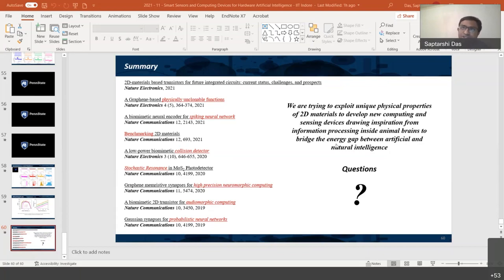But as you know, trapping and detrapping also has some other issues, which is the endurance, how many times you can cycle. That's a problem with NAND flash memories. You can hardly do 10^6. In our lab, we have been able to go up to 10^4 or 10^5. We are trying to continuously improve that. But the idea that I'm trying to present here is that even if you use some other form of memory along with your MoS2, you should be able to do a similar kind of computation. Your question is absolutely right, that we are taking care of charge trapping and detrapping, but any other form of memory will be equally suitable for this application. Okay. Thank you.